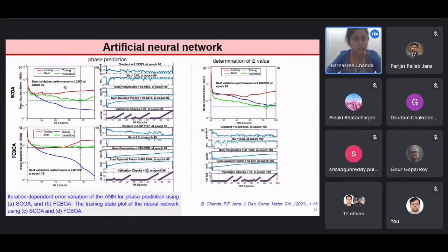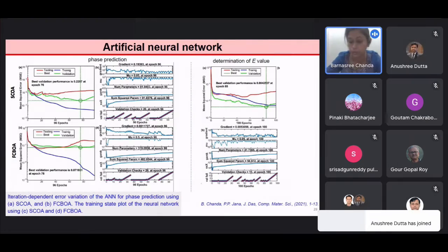So, for the phase prediction, the figure shows that the training plot for the mean square error has been continuously decreasing, but after a certain point, the validation and the testing errors increase, which shows that after this point, the network is overfitting. Therefore, we considered that this point is the best trained network. And these are the various parameters for the network training. But in FCBOA at epoch 76, we got the best trained network. Further, for the determination of the Young's modulus, at epoch 85, we get the best trained network.